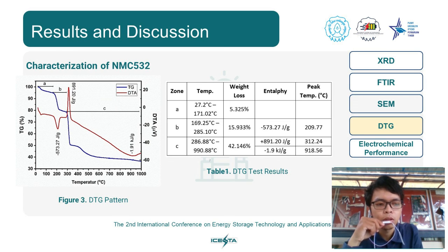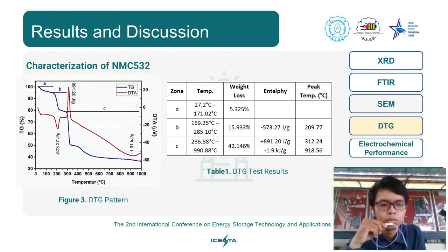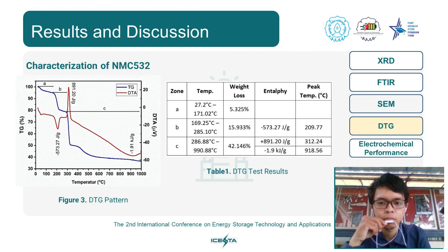In this zone, the oxalate group in the precursor will burn so that the NMC532 precursor will react with lithium from lithium carbonate to form NMC532 material. And in the red line, there are three peaks, two of which are downward peaks and one upward peak. The downward pointing peak indicates an endothermic reaction. Meanwhile, the peak facing up is an exothermic reaction.